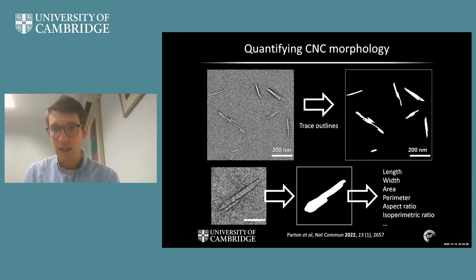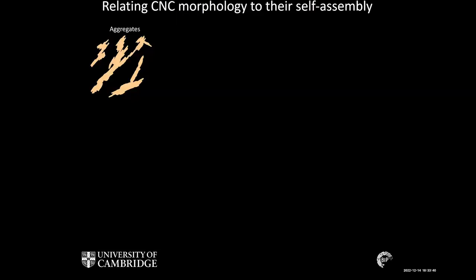And as a result of this analysis, we were able to classify the CNCs into 4 different populations. The reason that the sample is such a mess, such a mixture, is that it has different CNCs at different stages of breakdown. And so we called these subpopulations aggregates, meaning really large irregular structures; bundles, where there's just a few subunits connected together, a bit like the KitKat particle that I showed earlier; and crystallites, which are really the individual subunits of crystalline cellulose.